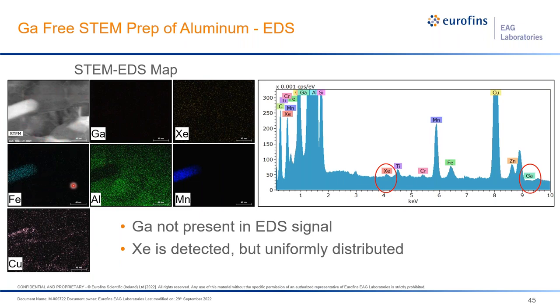You can see there's actually some other elements present like iron and manganese, and also there's some copper decoration along these grain boundaries. But overall, the xenon is actually uniformly distributed. No longer is it present in the grain boundaries themselves. You can see from the overall spectra that we have a small amount of xenon there and then no gallium present.